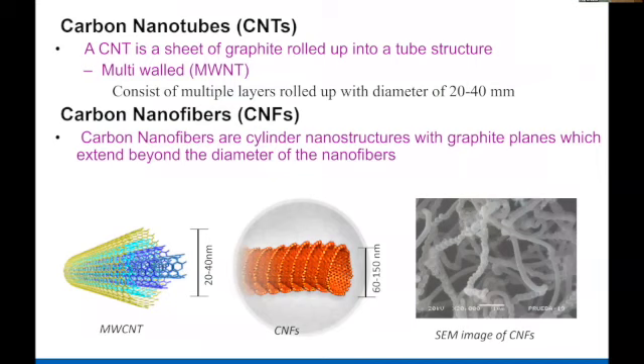They have amazing properties. They have a modulus as much as a terapascal and excellent conductivity. And what we are using are multi-wall carbon nanotubes or carbon nanofibers. And those of you who are working with graphene-based composites know that dispersion is a big issue because these fibers have a very large surface area. As you can see, they are about 10 to 20 nanometers in diameter and about a micron or so long. So dispersion is a big issue, and we spent a lot of time solving the dispersion. So now we are using ultrasonication and surfactant, and we can disperse them well.